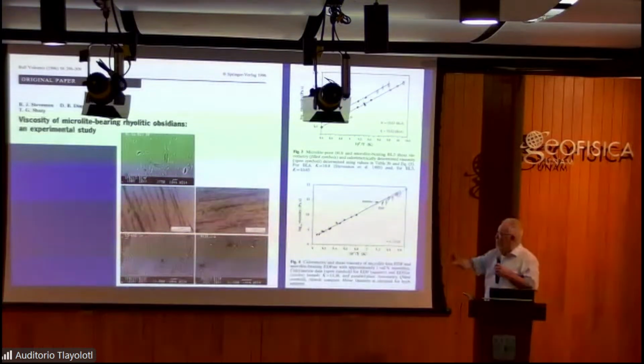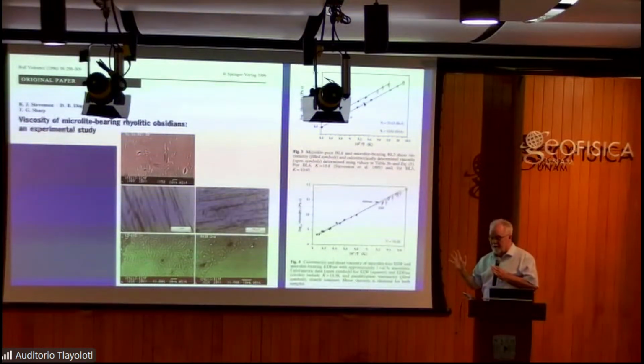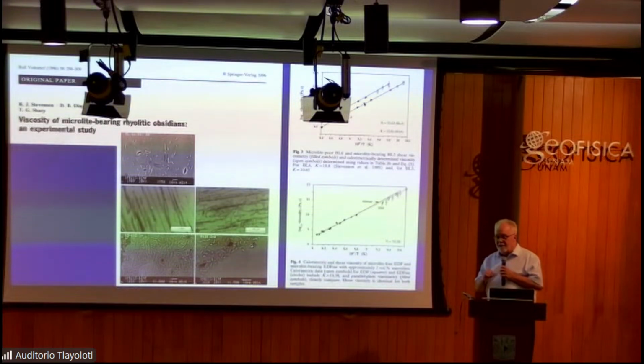Because the bulk measurement of viscosity is a bulk measurement. It's crystals plus liquid. Whatever the relative contributions are, everything is being deformed macroscopically. So that's one value. Now I need a second way to measure viscosity where I'm only going to get the viscosity of one of the two phases in the glass with crystals. I'm going to get the viscosity of the glass or the liquid itself without any influence of crystals. And how do I do it?